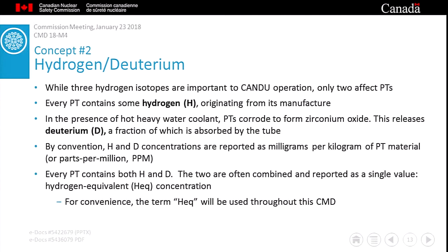Corrosion reactions result in two things. First, a thin layer of oxide appears on the pressure tube surface, and second, a small amount of the deuterium from the corrosion reaction finds its way into the tube. The amount of deuterium is so small, it is reported in parts per million. For simplicity, rather than talking about a given pressure tube having so many parts per million of hydrogen and so many parts per million of deuterium, industry rolls the two into a single value and talks about the hydrogen equivalent concentration, or HEQ. So for the rest of this presentation, you'll hear me talk about HEQ.